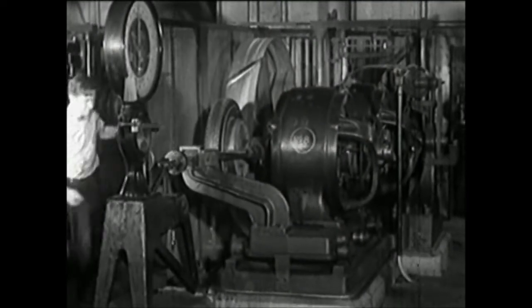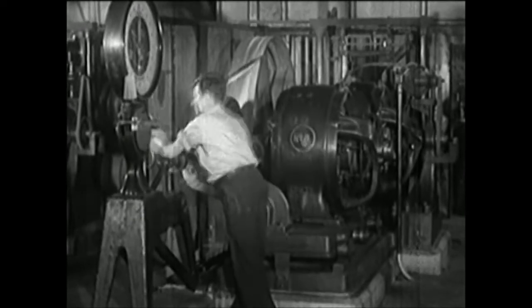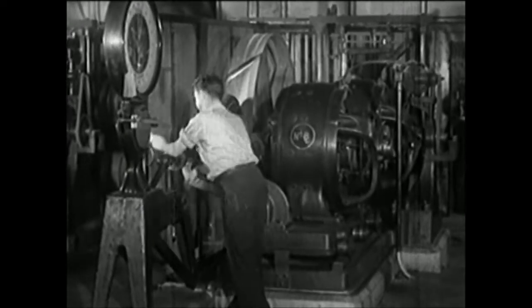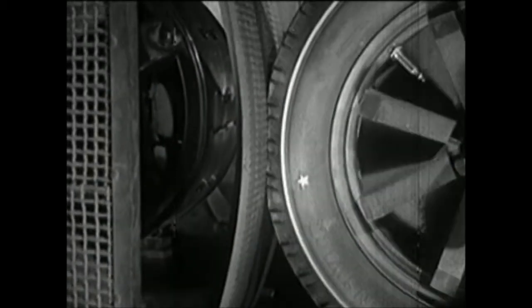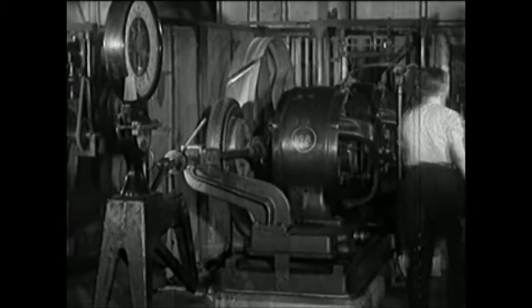On the Sprague machine, the ordinary tire doesn't last very long, because here is a test that compares only with the continuous run at incredibly high speeds over the roughest possible roads for thousands of miles without a stop. The tires are forced against a large dynamometer wheel at carload weights. The rough surface provides traction for the tires, which pull against the dynamometer load. Heavy iron cleats fastened to the large wheel pound the tire incessantly throughout the run. For the equivalent of thousands of miles, these tires are driven on and on for days at a time.